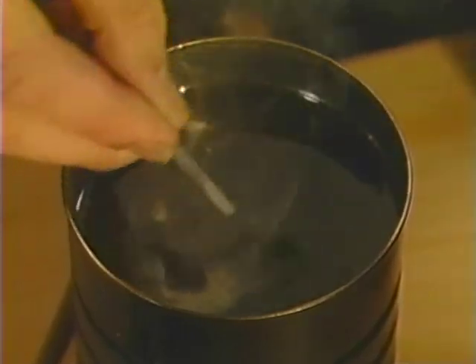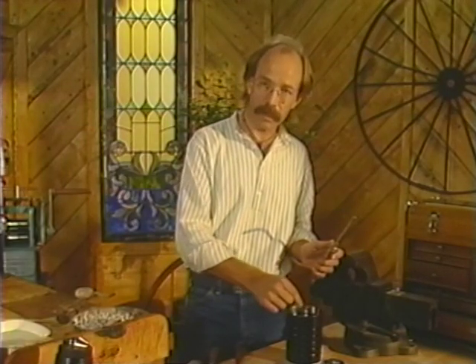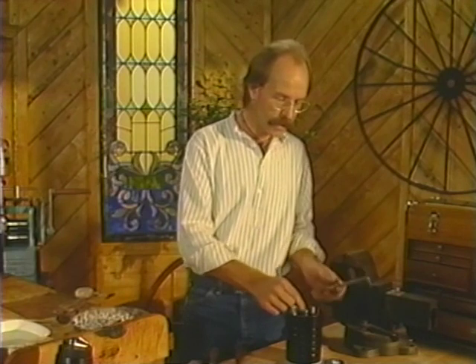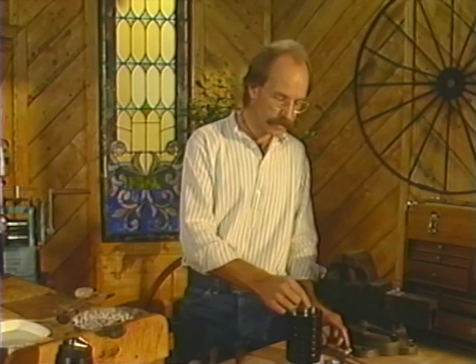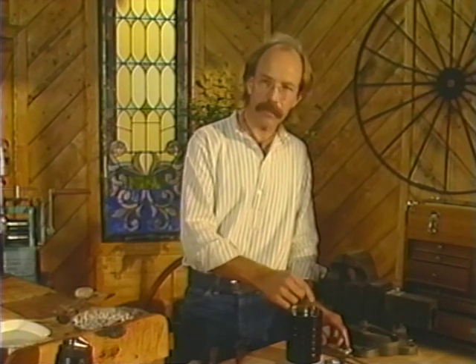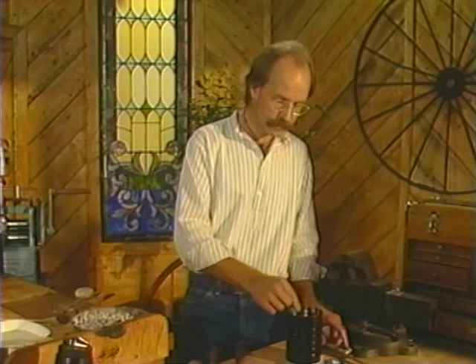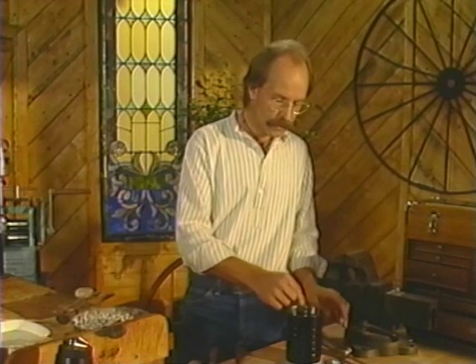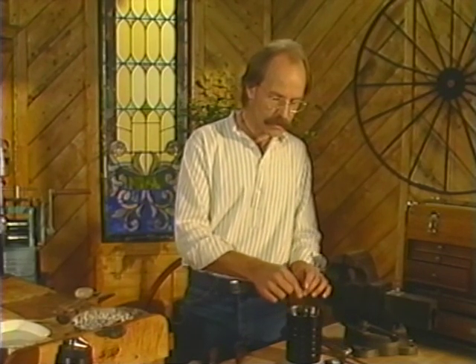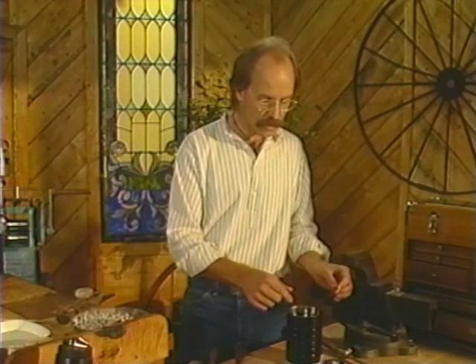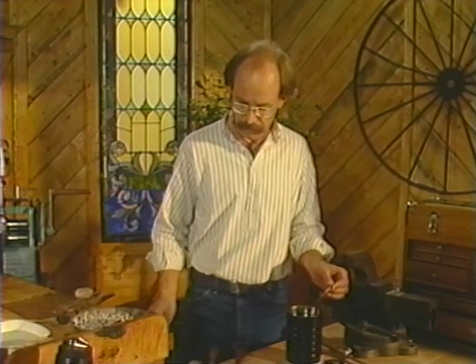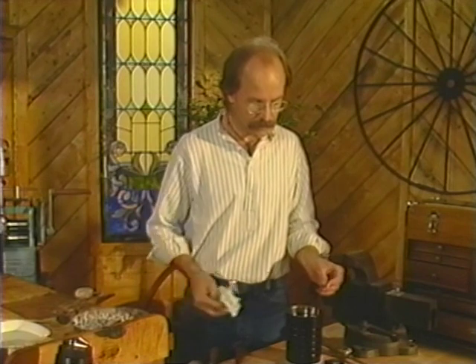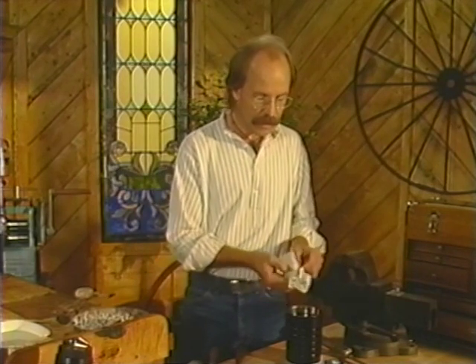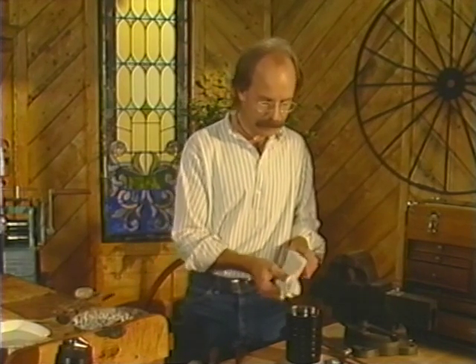The stirring is important. If I plunge the tool in without stirring, it's immediately surrounded by an envelope of hot oil, and that defeats the purpose. By stirring, I'm constantly bringing it into contact with fresh, cool oil. I'll keep it there until it has cooled sufficiently to hold. Clean it off, and then check it.